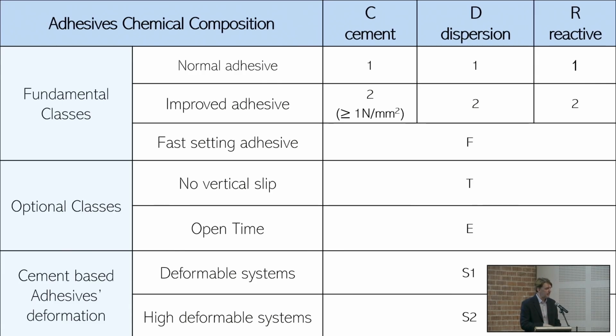It's very interesting because in a condition of high temperature or high humidity, the extended open time helps the applicator to maintain fresh the adhesive. Imagine this place here, outdoor. And then they have to fix tile. And then they start to apply the adhesive here, maybe not in a small way, but they cover half of that. By the time they fix tile here, and register, and then here, and then place the space over there, the adhesive is done, already done, because of the humidity, because of the weather, okay? The extended open time helps you to keep fresh the adhesive, not forever, but for 20-30 minutes after the application.